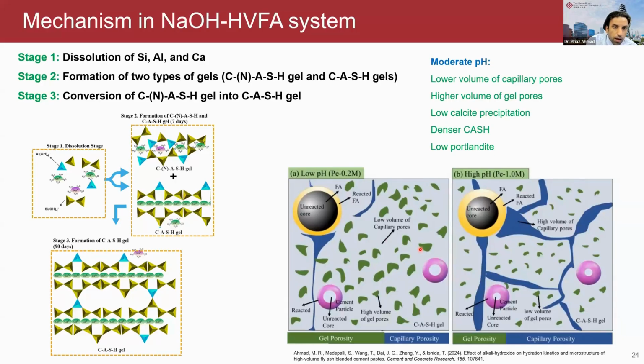when we use a high amount of sodium hydroxide, there is a significant increase in capillary pores. So actually, using sodium hydroxide or this alkali treatment is not always beneficial. We have to very carefully optimize the optimum content of sodium hydroxide. If you see these blue channels, they represent capillary pores, and they are much wider as compared to these figures on the left side, which show that capillary pores are much lower there.